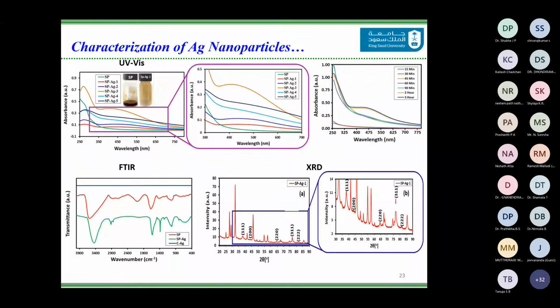And the root extract at lower volumes, between 0.5 to 3 ml, you get amazing nanoparticles. However, when you increase the root extract volume up to 5 ml, the nanoparticle formation will cease. There is no further change. So for this study, we have used a root extract of 3 ml as standard.